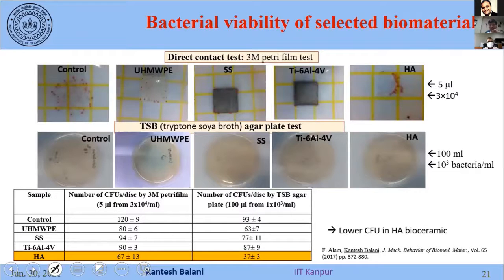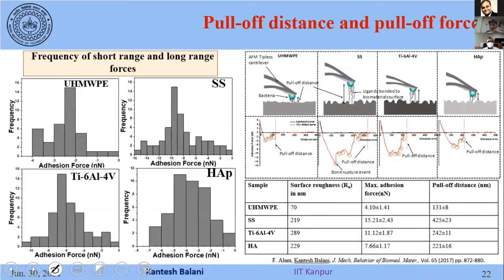There are other quantification techniques conventionally available, and that is the direct contact test and an agar diffusion test, agar plate test. In both of them, I will see that the colony forming units are minimum. It means the minimum bacterial colony is being formed in hydroxyapatite, which is ceramic. So that will be my ultimate choice. Conventional knowledge tells we should go by selecting hydroxyapatite. It ignores everything else. But now what we have gotten from our results shows that polymer is showing the